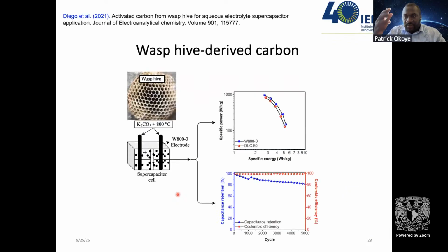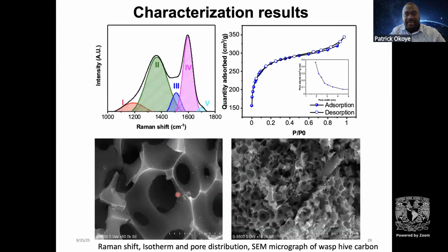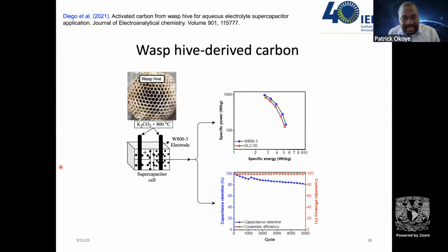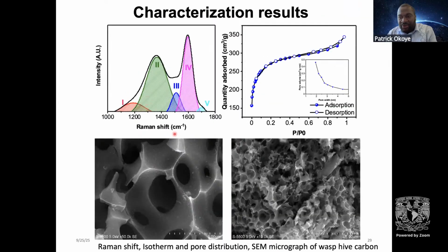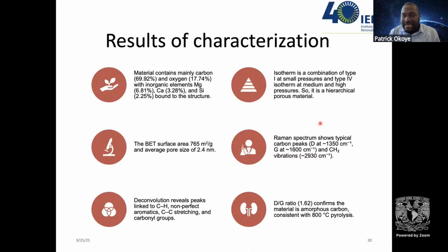Hence, we use wasp hive to produce activated carbon. A student here in Mexico produced this material, and this material is very fascinating because the wasp hive, which of course looks like the honeycomb of the bee, in the micrograph of this material also has interconnected pores in it. And our isotherm, of course, is a combined isotherm, of types 1 and 4. So the material contains about 69% carbon and 17% oxygen with some inorganic elements.